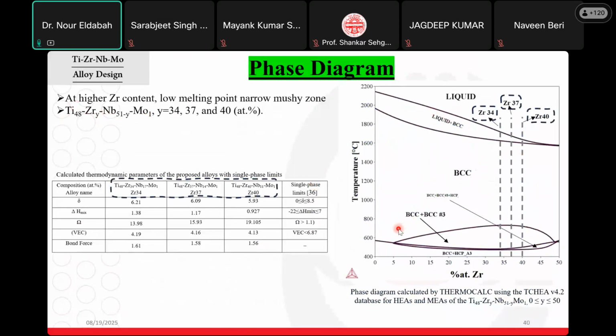So what do you conclude from this phase? We have allocated three compositions in this region. Why in this region? One of our problems is the high melting point of these systems, because we have niobium and molybdenum. Niobium will increase our melting point, but if we increase the zirconium content, we will allocate our alloy in the low melting point region. So you should consider this.